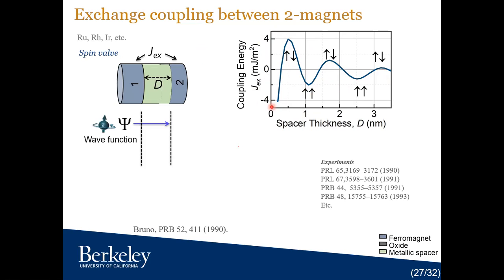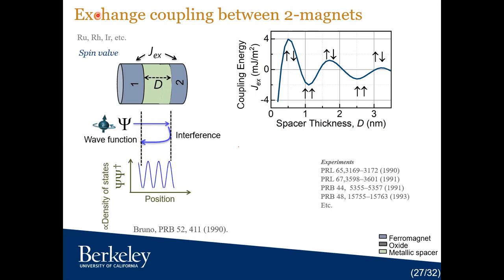And the physics is quite simple. We have equilibrium electrons inside the magnet, and they are spin polarized. So we have a spin dependent wave function that can go from one interface to the other. It gets reflected, comes back, and creates an interference pattern, just a wave interference pattern. So you will have bright spots and dark spots. When you change this middle layer thickness, you are basically changing the interference pattern. That's why you see a periodic nature. So this is a bright spot, dark spot, bright spot, dark spot, and the magnets change accordingly because you are actually changing the density of states. It was theoretically explained very well in this paper. You can look it up if you're interested.